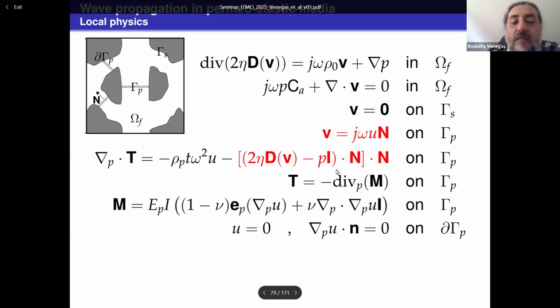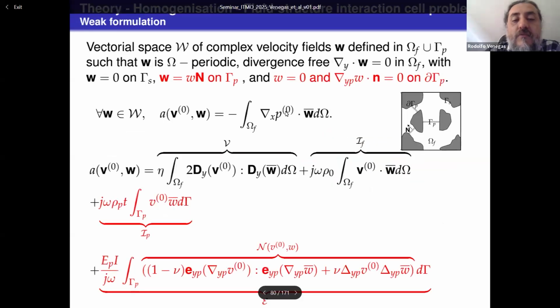And here we have the conservation of momentum for the plate that is loaded by the difference between stress on both sides. And again, this is the rest of the constitutive equations of the plate, and the boundary conditions indicating that the plate is clamped on these edges. So the physics is: a pressure wave will generate a velocity field, this velocity, and also a stress field. The stress will set these plates in motion through this term here, and when these plates move, they will affect back the fluid flow in this case. So we get a local fluid structure interaction problem whose variational or weak formulation is shown here.